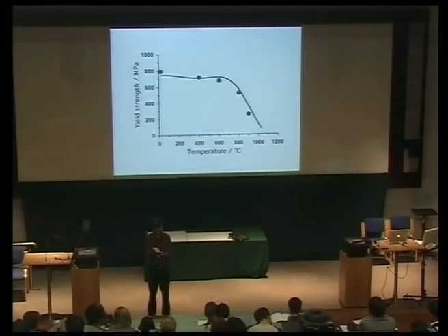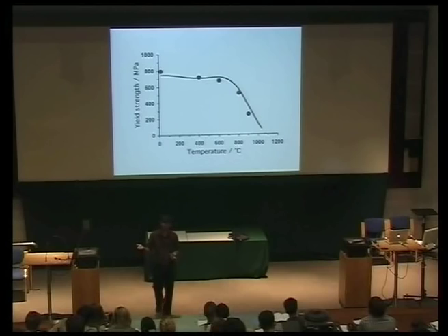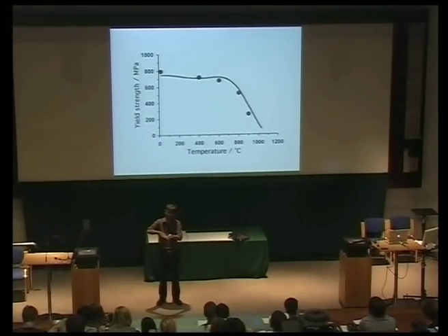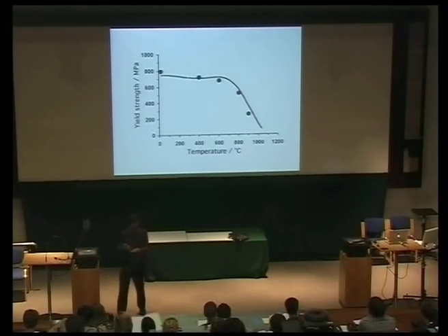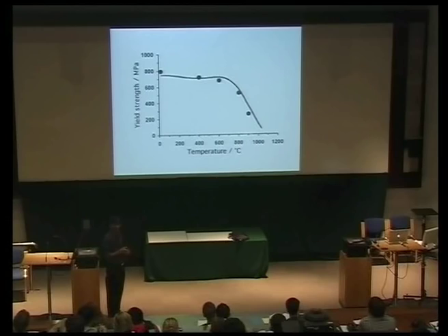So the dislocations tend to cross-slip from the 111 to the 100 plane. And in doing so, they get into trouble because you've got an intersection between planes, and part of the dislocation lies on the 111 plane, another part on the 100 plane, and that makes it difficult for it to move. If you've got a dislocation with a fault in between, and a part of it is on the 100 plane and another part on 111, it clearly finds it difficult to move. So as it cross-slips onto the 100 plane, you maintain the strength because it becomes difficult for it to be mobile.